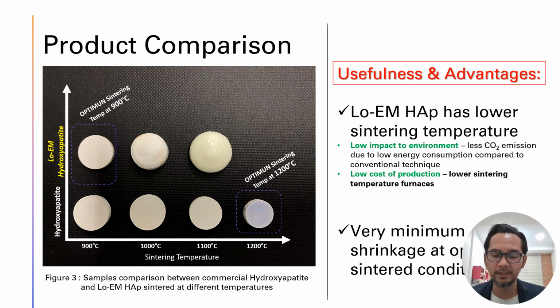So what are the usefulness and the advantages? Lo-EM HAp has a lower sintering temperature, low impact to the environment, and less carbon emission due to low energy consumption, compared to the conventional technique that uses higher energy consumption because we sinter at a much higher temperature. And also the low cost of production. I think our partner from the industry really likes it, really loves and enjoys this. And there is very minimum shrinkage at the optimal sintering temperature of 900 degrees Celsius for the Lo-EM HAp and 1200 for the optimum of the conventional method.